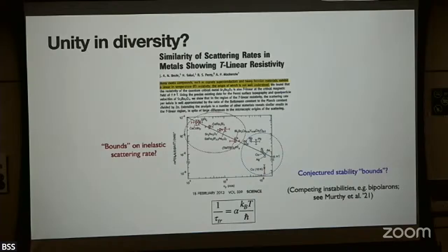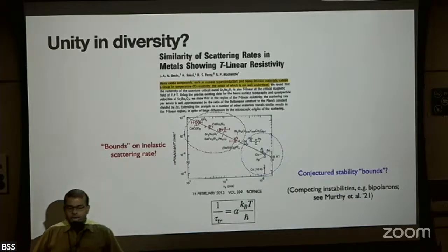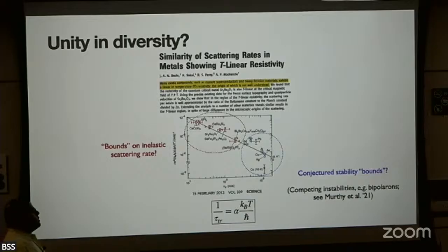Okay, the trouble is it's usually very difficult to have a very precise definition of what you mean by a scattering rate. So, okay, and I'll talk a bit more about that. That also touches on things that Peter Armitage talked about during the first week. But one of the early papers that really demonstrated the possibility that there might exist such Planckian bound goes back to this paper by Andy Mackenzie and collaborators, where they extracted a scattering rate. Okay, so now because this is going to be somewhat important, I'm just going to briefly tell you what they did. Now, on some level, if you want to extract a transport scattering rate, maybe the best way to do that is from optics experiments.